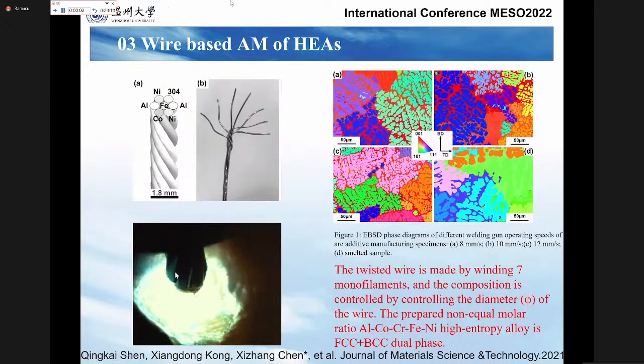Also, you can see from the high-speed camera made for the cable wire, when it melts, the wire will have a self-rotation, which is very good, especially for HEA, because I said this has segregation. So we can have a stir or make the composition more even. So we use it like this in the paper. Okay, the twist wire is made by 7 single wires, and the composition is controlled by the diameter. So that's what we did.